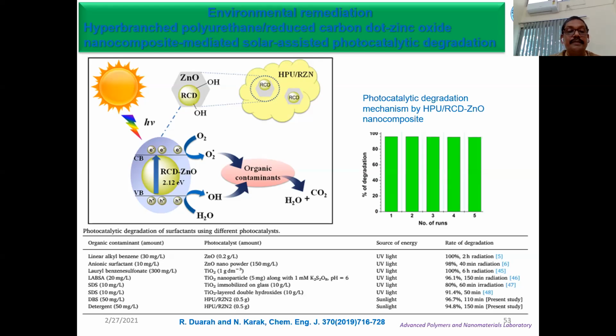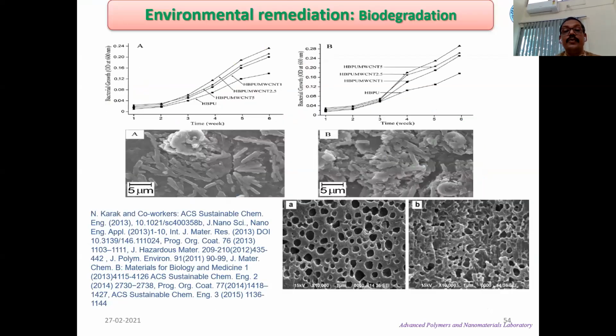We mixed these nanocomposite films and exposed them to sunlight. Because they have a low band gap of 2.12 electron volts, UV light from the sunlight is absorbed, and excited electrons generate holes and electron pairs, which result in hydroxyl radicals and superoxide radicals, ultimately oxidizing the organic contaminant to carbon dioxide and water, thus cleaning the contaminated water. All these nanocomposites are also biodegradable, and hence will not cause any garbage issue to the environment.